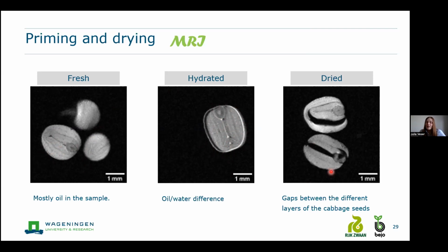And for the dried ones, we see again quite evenly distributed signals, so basically mainly oil. But what's also very interesting here is that we see quite big gaps in between, which indicates air. So that was quite interesting to see for us, that actually we have quite big air gaps inside the dried seeds. All right, so these are all the methods we want to use to validate our model. Let's have a look how the model performed.